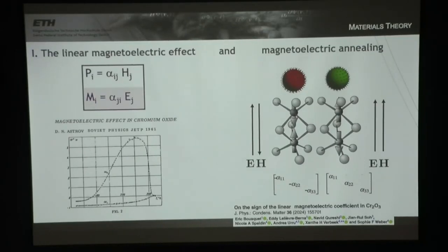It's a bit complicated, particularly because of neutron diffraction. I don't know if there are any neutron people here. You guys use magnetic moment and magnetic spin interchangeably, which is very confusing. But anyway, we think we even understand the sign. But importantly, we get opposite signs of the hedgehog, which correspond to the opposite antiferromagnetic domains. And in general, if you just have a general antiferromagnet, it's not so easy to pick a particular domain, right? There's not a generic conjugate field for an antiferromagnet, but there is for a magnetoelectric, and it's a composite field of E and H.